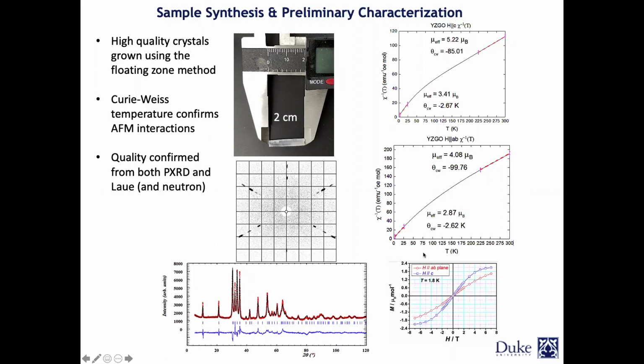What would you expect to see in the case of, for example, ferromagnetic ordering, antiferromagnetic ordering, and all of these things? Any sort of phase transition, you have to start to see a sharp anomaly. For ferromagnetic, it's different than antiferromagnetic. But in this case, you can see that we didn't see much happening. So it shows that down to the very lowest temperature, the system stays disordered, because if it had gone into an ordered state, we would have seen a sharp anomaly in the data.